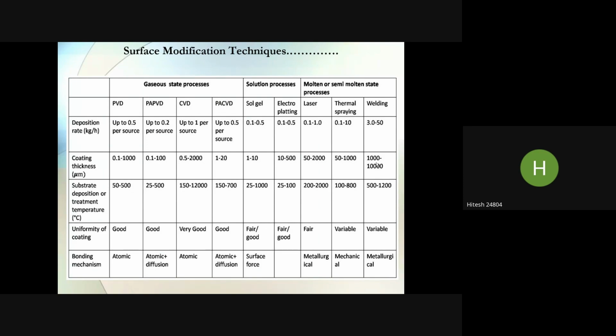Otherwise, in case of wear and erosion, because surface engineering is more likely related with wear and corrosion applications, we use a layer of 2 to 300 microns only. But let us say you want to develop a thick layer over the rollers which are used in the cement factory. Over there you have to use hard facing. That is why welding electrodes are used over there for the remanufacturing process, for the repairing process, because thick layers are required. So that comes under welding. Otherwise we call that cladding, because there are two terms, coatings and claddings. Cladding comes under this category.